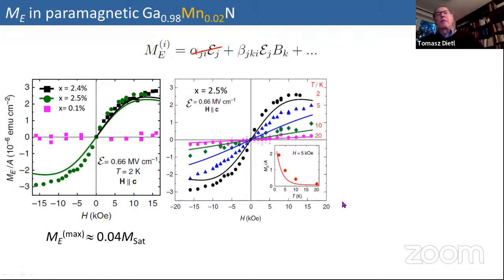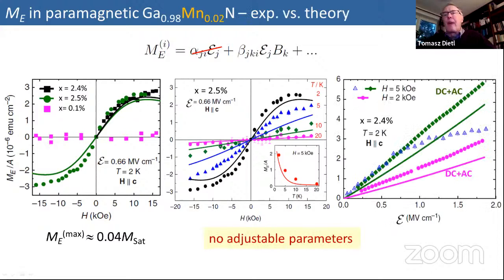We can study as a function of temperature, and the effect decays with temperature. Again, here it is not magnetization, but electric field induced magnetization, the magnetization which is in phase with the electric field which we apply. We can also study this as a function of electric field, and then at weak field we have this linear dependence as predicted. So this confirms the linear dependence at weak magnetic fields and confirms the linear dependence as a function of electric field.